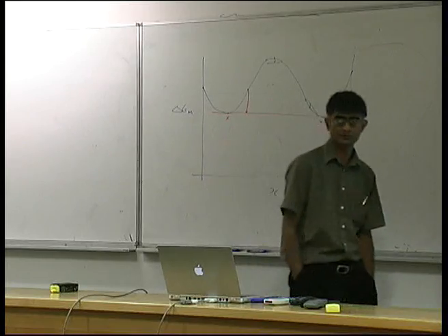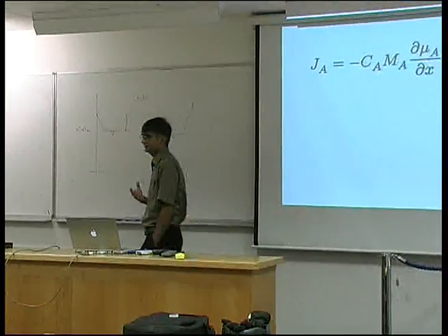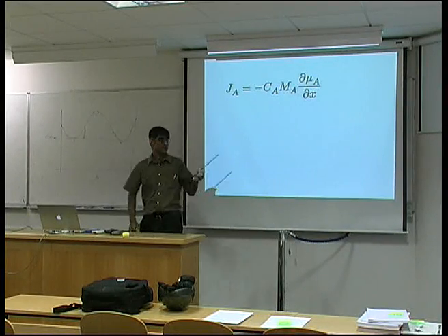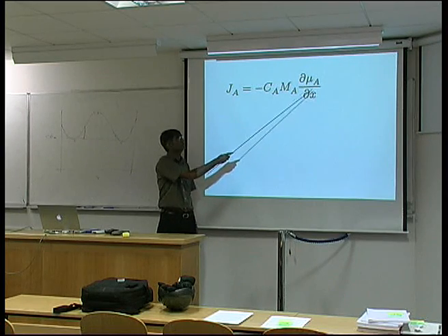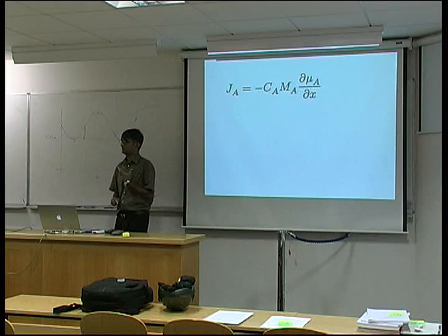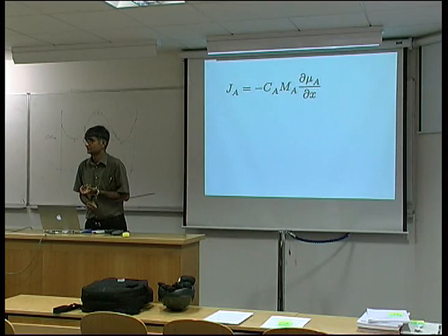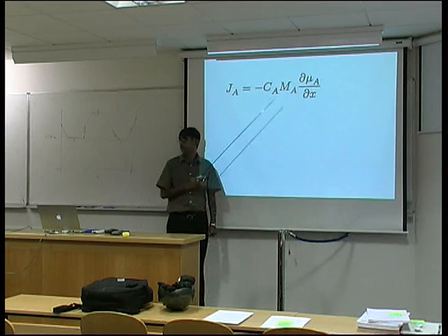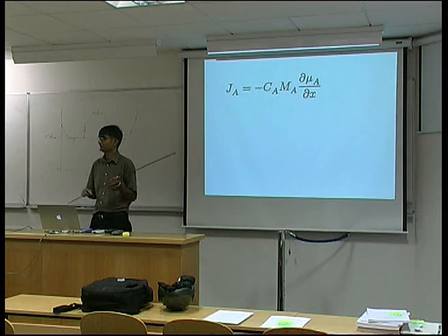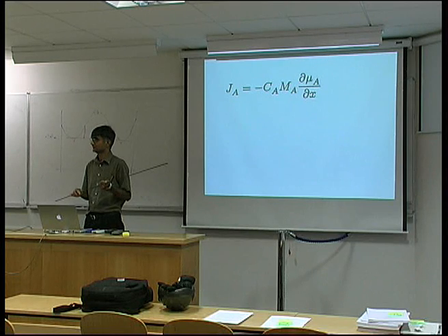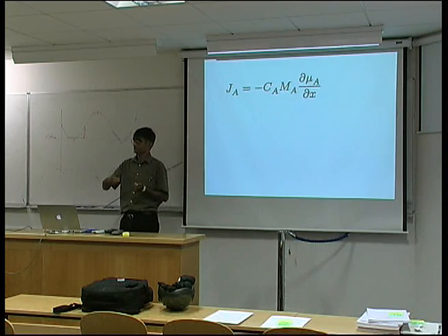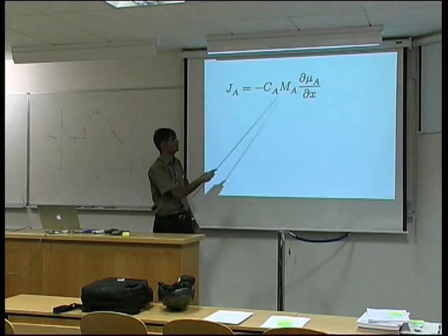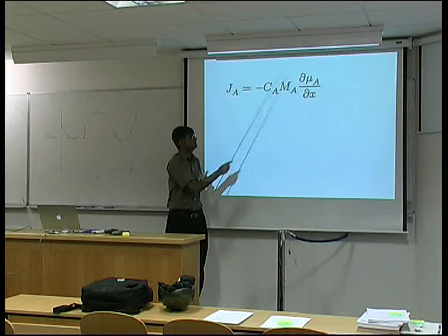Let's deal with that more formally. We want to write the flux in terms of a chemical potential gradient. The gradient of chemical potential is written where X is a distance and mu_A is the chemical potential of A. But remember, mu_A is per mole of material - the free energy of a mole of A atoms in that solution. So I need to multiply by the concentration of A in order to get the gradient of free energy.